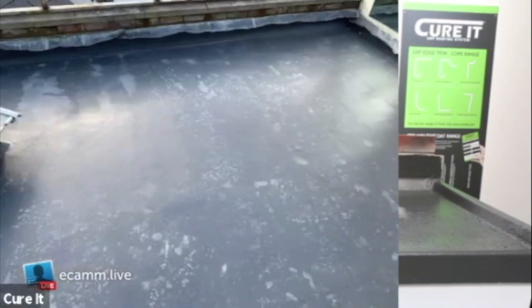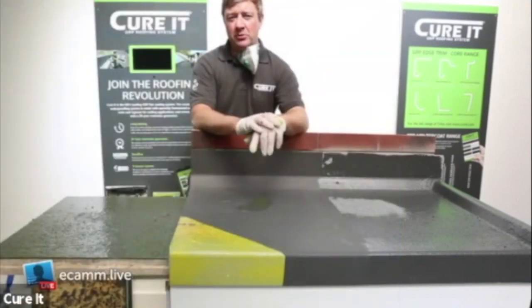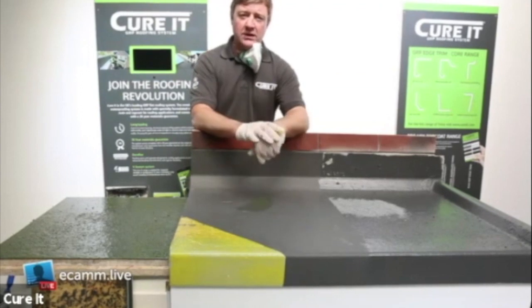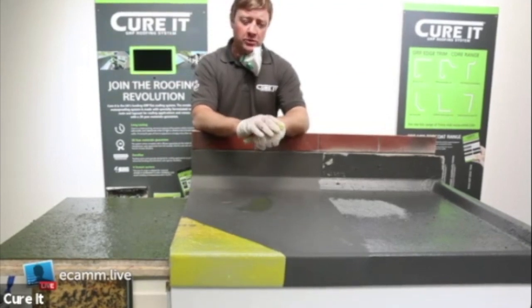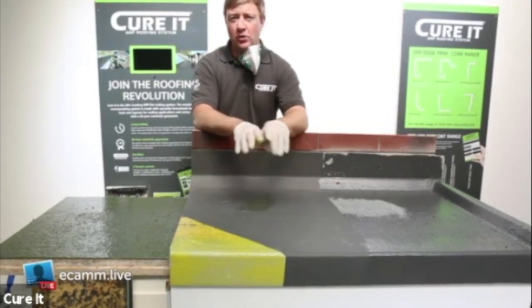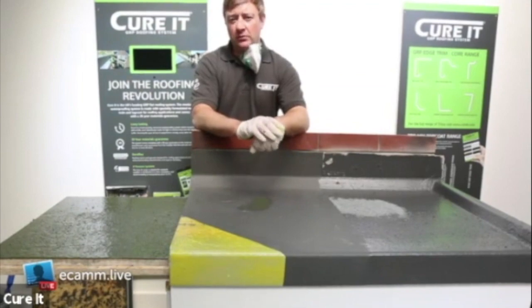This was left overnight, and obviously water droplets just lying on. You can see the stain, the white stain there, which is evident. And that is where the top coat hadn't fully cured, and the water had just contaminated that surface as well. So it's important, obviously, pick the right time of day, pick the time to get it done, and you can go over the top with your top coat, but obviously keep it when it's dry. Any water in it will contaminate your top coat as well.